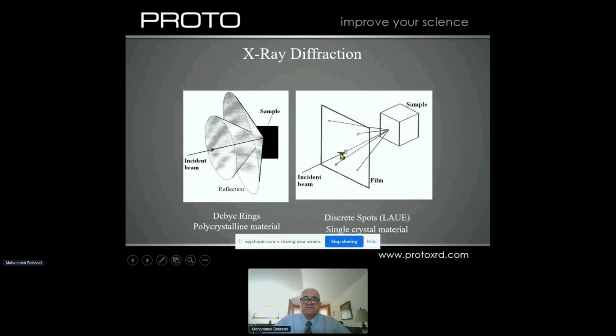How do they verify the direction of these blades now? We use X-ray diffraction. In contrast with polycrystalline materials, where we get diffraction coming from multiple grains oriented randomly in the material, here we see only one grain, and we see spots, and each spot corresponds to an HKL plane in the material. And it depends on the orientation of, let's say, the crystal. These spots will move with it.